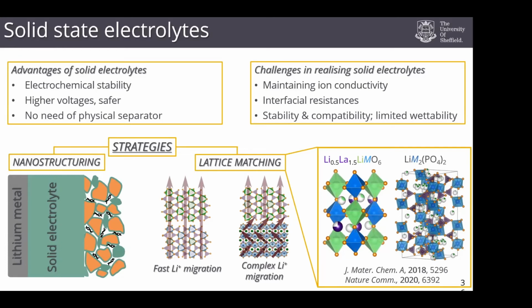The metal here, by judicious choice of that metal, you can end up with something that's redox active, so it can act like a cathode, or something that's non-redox active, but is ionically conducting, and that can act as an electrolyte. We've also made some phosphate-based materials that are based on an NASICON structure. And again, just the choice of that metal means that you can either be a cathode, or an anode, or a solid electrolyte.